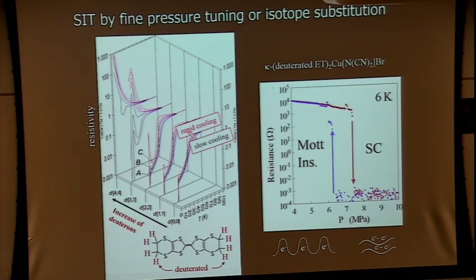This is the isotope effect. Usually the isotope effect is very subtle, for example a small change in TC or some transition temperature. But in our materials, the isotope effect causes a metal-insulator transition or superconductor-insulator transition. It's huge, because these materials reside on the verge of the Mott transition.